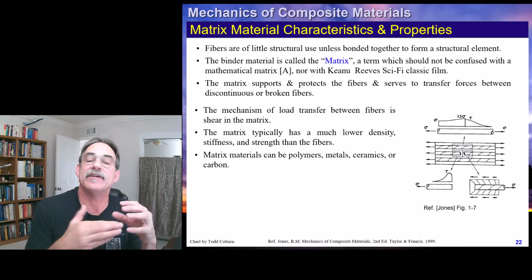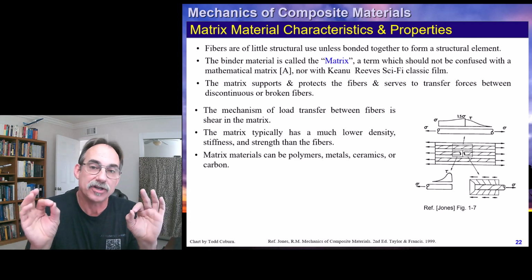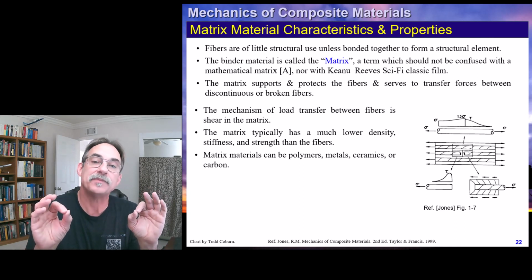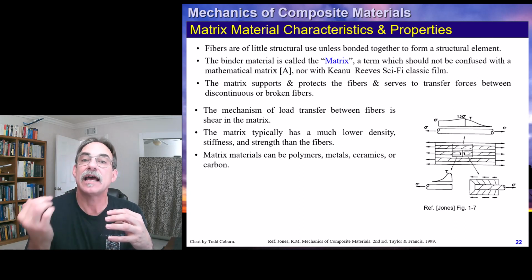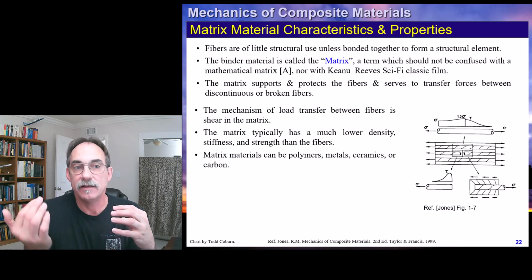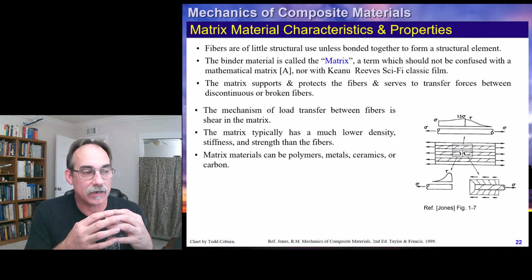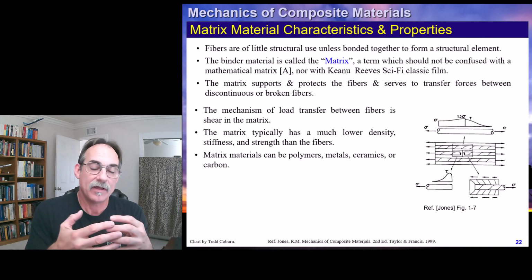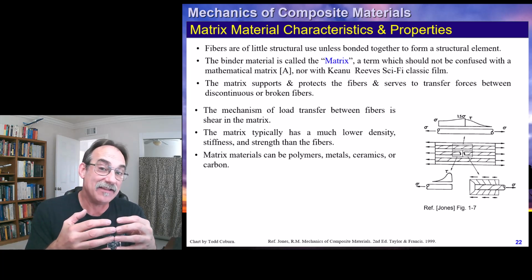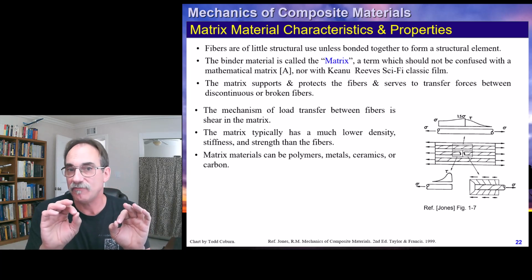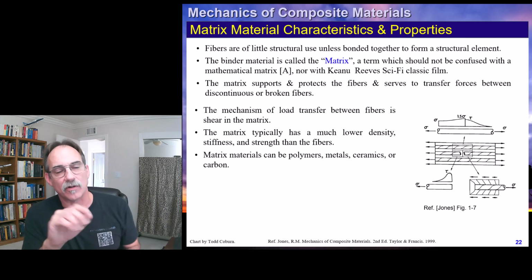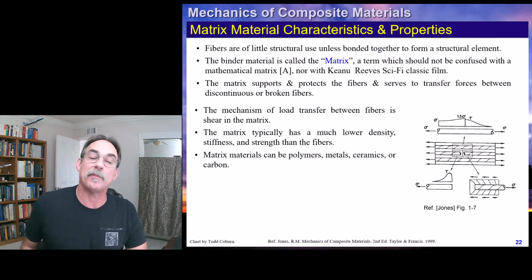That's actually going to affect our properties, but because we're measuring the properties with all these discontinuities randomly distributed throughout the material, any given defect is not going to have nearly as much effect, because we already have accounted for a lot of defects within our material. Actually, Jones does a really good job of talking about that in his text.